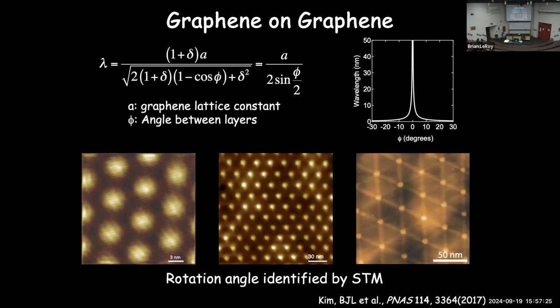If I go and show you what it actually looks like in the STM, here's 3 different images of what this moire pattern, this twisting, looks like in graphene sheets on top of each other. It's not too hard math to figure out what this wavelength should be as a function of twist angle. It basically boils down to going as 1 over the sine of the angle between them. Here, you can see the size scales, 3 nanometers, 30 nanometers, 50 nanometers. So we're changing the twist angle. We're getting smaller twist angle as I go to the right here. And at first, you can kind of maybe see the little graphene hexagons in here, the little tiny hexagons. And then there's this periodicity that is on the order of 5 nanometers in this guy. The periodicity now, you can no longer even see the atomic lattice, but we have about a 30 nanometer periodicity here.